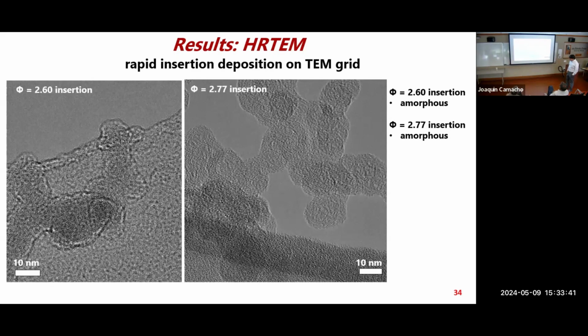Okay. So another sample collection method we used was rapid insertion of the TEM grid so that we can just dip in and out, and it should coat the substrate with particles. And indeed, we did get these particles, and it's probably what we're observing in the flames. This orange color is probably these typical soot particles. So the particles that are flame formed, naturally born in the flame, are probably soot. That's what this structure is. An aggregate fractal-like structure with this turbostratic-like structure. It's no longer these straight graphene layers, but this is typical of what we see for soot. And when we do this rapid insertion directly in the flame, we do capture evidence that it is probably soot forming in the flame.